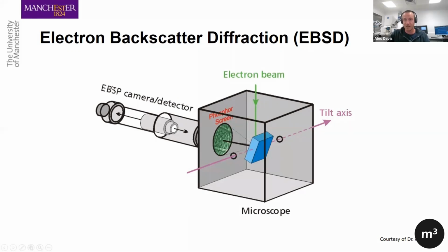So this is a standard EBSD setup in an SEM chamber. So what we have is a technique to measure crystal orientations in the SEM and map phase distributions. And we do this by simply attaching our EBSD camera to the side of the chamber. We have our sample tilted here, and we'll go through a bit later the importance of tilting. Our electron beam hits our sample. We get backscattered electrons that come out of the sample and hit this phosphor screen on the detector. And this converts the diffracted electrons into light, where we can now see this pattern, and it's collected by the EBSD camera. And then by rastering the electron beam, we can collect a map of information, whether that be phases or crystal orientations or both.